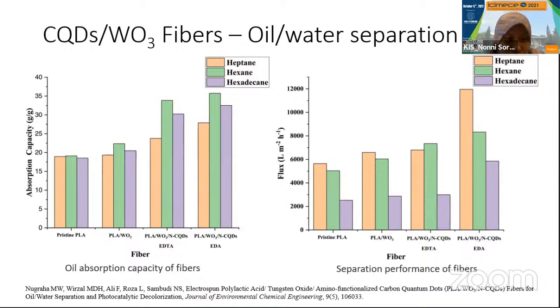And from the test that we did related to the oil absorption capacity of the fibers, the one that we incorporated with the tungsten oxide and carbon quantum dot shows higher oil absorption capacity compared to just pristine polylactic acid. Okay, and the hydrophobicity and oleophilicity of the fiber mats can also increase the flux of the heptane, hexane, and hexadecane that goes through the fiber mats. Right? So overall, we can separate the hydrocarbon from the water fully, almost 100%, and we get a good flux from the separation performance.